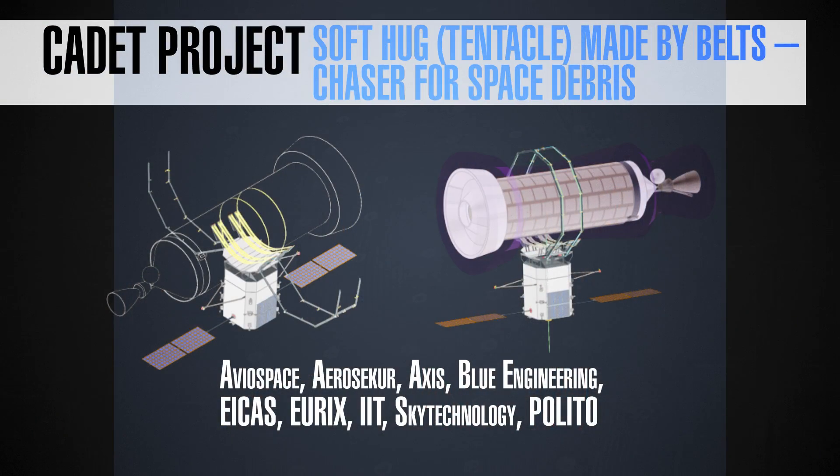We selected nanocomposite materials to realize the pressure sensors giving the signal of contact between the chaser and the exhaust fuel tank. We chose nanocomposites instead of standard solid-state sensors because, rather than a crystalline ordered structure, you have an amorphous system with a fully dispersed distribution of functional fillers inside a matrix. This is important because highly energetic particles or micrometeorites that hit and damage the material cause huge damage to an ordered structure, while an amorphous system is more resilient to this kind of damage.